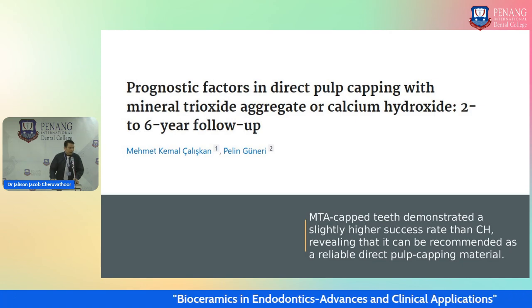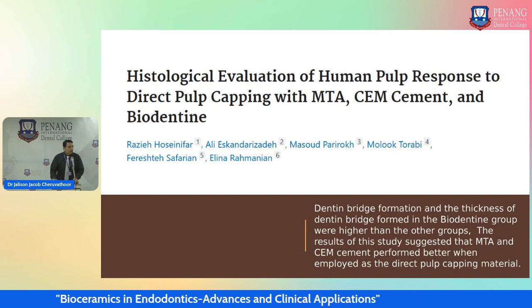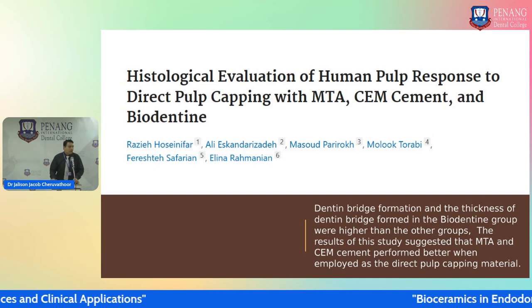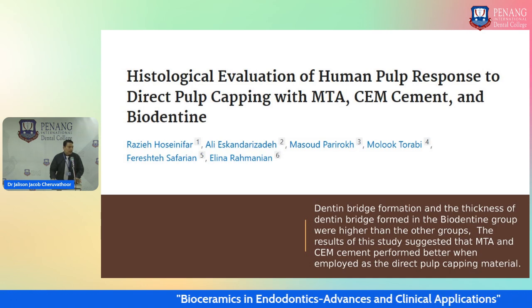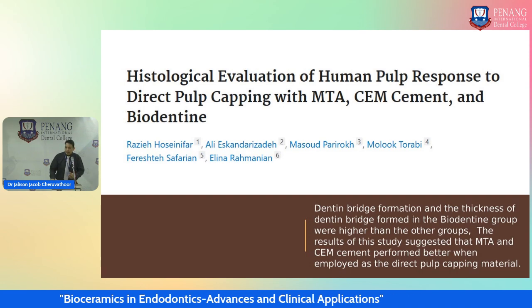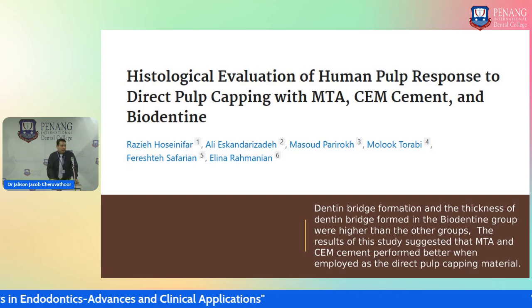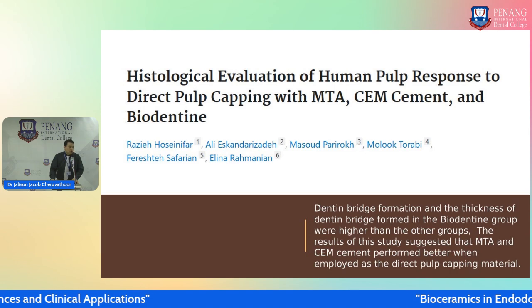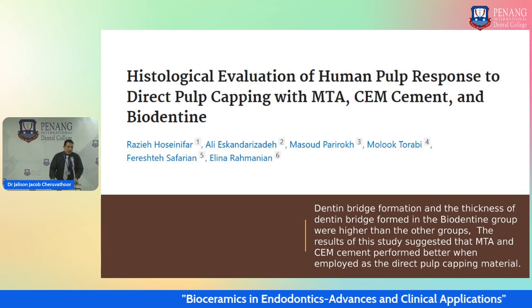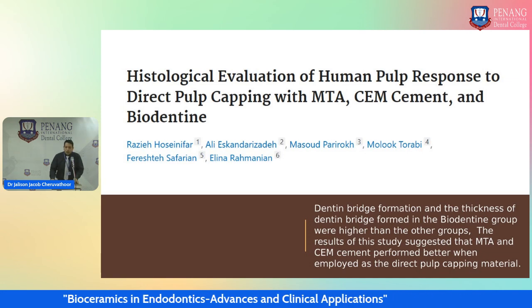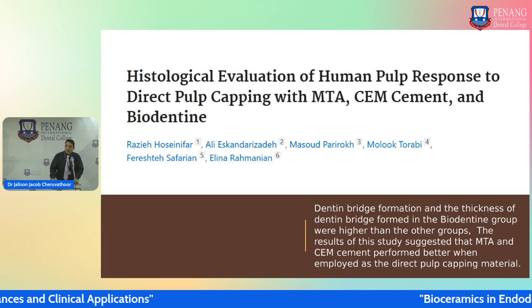Another study showing histological evaluation of human pulp response to direct pulp capping with MTA, calcium enriched mixture cement, and Biodentine. In this study, calcium enriched mixture and MTA employed as the direct pulp capping material have better properties compared to Biodentine. The reason, even though Biodentine forms good bridge formation and thickness of dentinal bridge, is that it is still not considered as better than CEM and MTA. In this study, Biodentine showed a lot of inflammatory response compared to the other two calcium silicate cements.